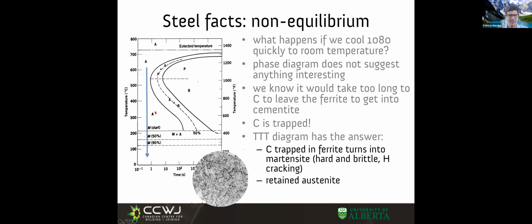Isn't this interesting? The austenite is transforming into martensite, but everything's so twisted and difficult that sometimes the same strains in this transformation, the same internal deformation, cause enough force to keep some of the austenite—called retained austenite—living at room temperature. Although in theory austenite should not exist at room temperature, when we have these very complex transformations, they induce stresses and strains that prevent it from transforming completely.